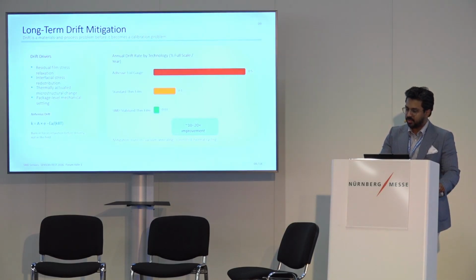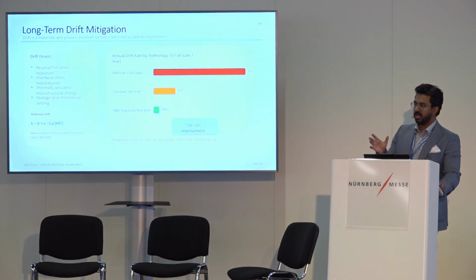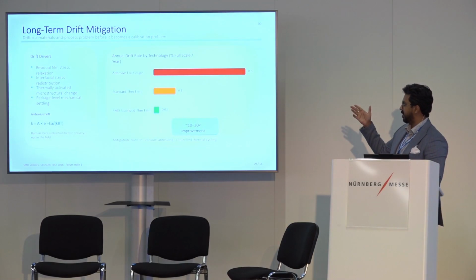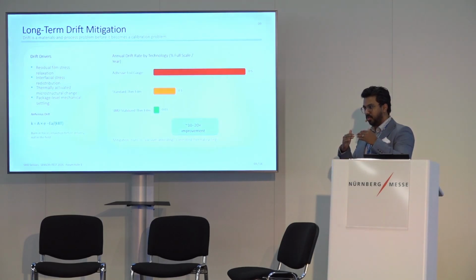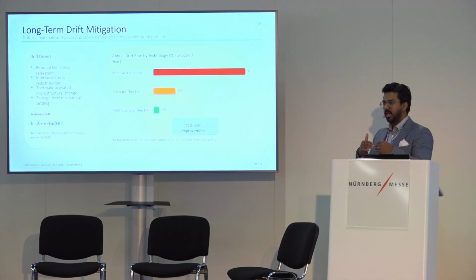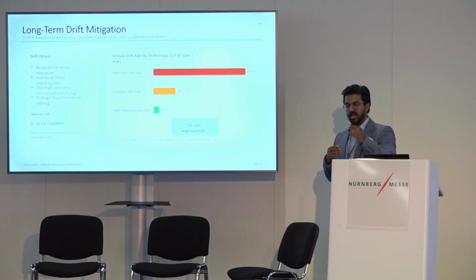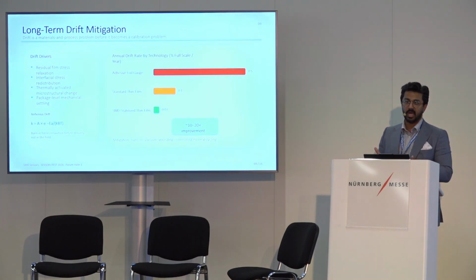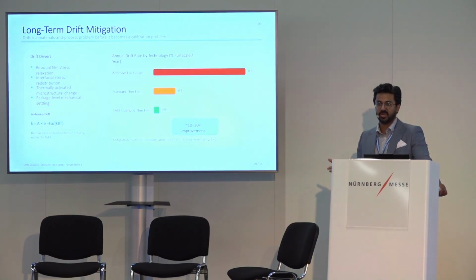The chart on the right shows the result of these drift drivers and the optimization after we perform. So let me give you an example of how one of these drift drivers works. For example, the residual film stress. When we do thin film on a substrate, following my previous slide, if the thermal coefficients don't match, it creates a stress and strain on the substrate, which we call the phantom strain. And that is usually not looked into calibration until you are looking for extremely high resolution. And think about high temperature applications, where you're looking at high resolution at high temperature and at a certain pressure range that you want to validate.